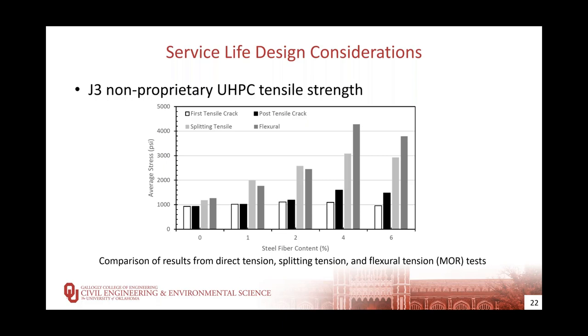In most other testing, we use the typical 2% steel fiber content along with 1%, 4%, and 6% fiber contents for comparison. It can be seen here that the first tensile crack stress in the direct tension test is fairly consistent across the fiber percentages and that it is primarily controlled by the matrix. The maximum tension strength for all tests increases with increasing fiber content up to 4% steel fibers, after which there is a slight decrease, likely related to the consolidation of the mix.